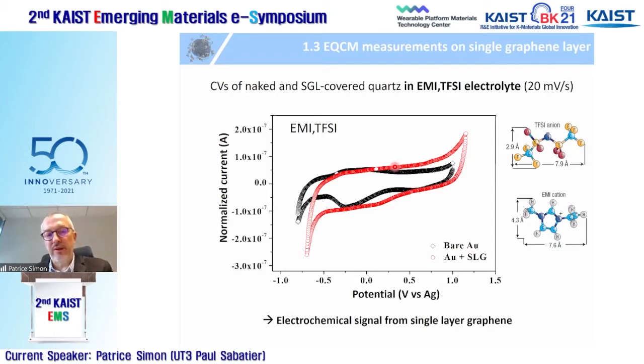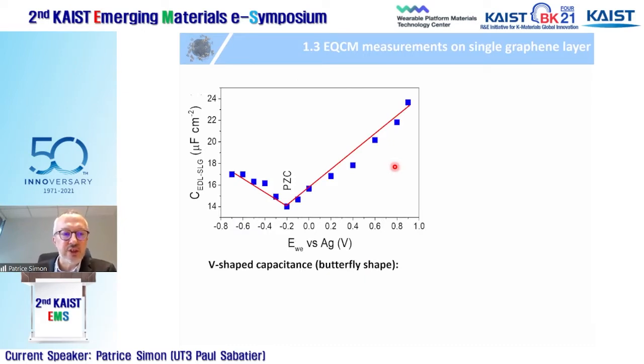Now what we did, we polarized this electrode at constant potentials, and we measured the double layer capacitance, just to try to plot the change of double layer capacitance versus potential. And this was done by using electrochemical impedance spectroscopy. And this is the change of double layer capacitance of a single layer graphene versus the potential of the graphene. So as you can see, we have a V-shape capacitance change, what was called in the literature a butterfly shape.